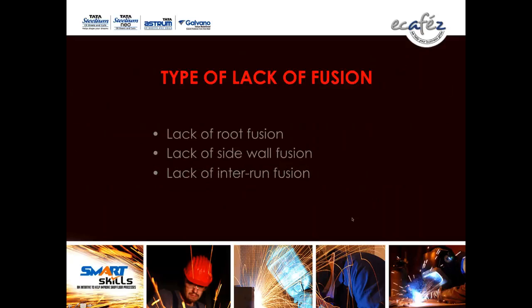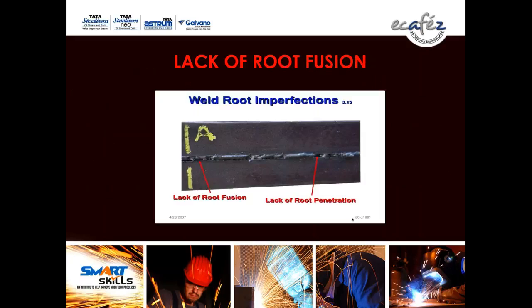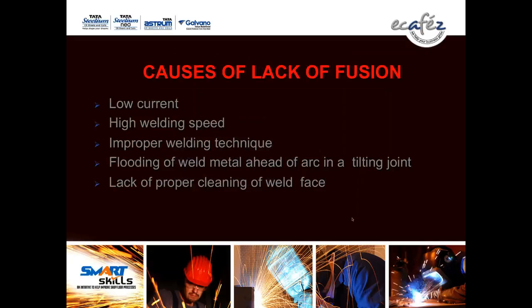So next type is lack of fusion. Lack of fusion may be of three types: lack of root fusion, lack of sidewall fusion, lack of inter-run fusion. See the pictorial view of lack of root fusion. Here, lack of root fusion, and the other portion is lack of root penetration. Causes of lack of fusion: low current, high welding speed, improper welding technique, flooding of weld metal ahead of the arc in a tilting joint, lack of proper cleaning of the weld face.